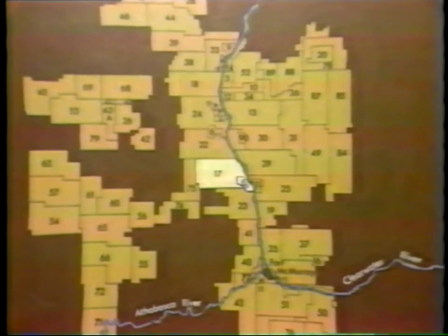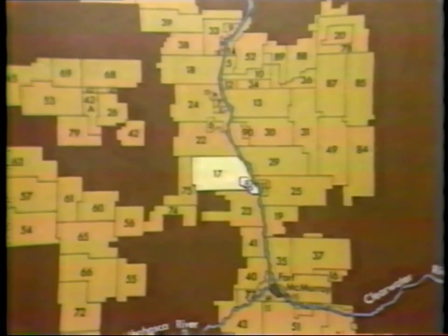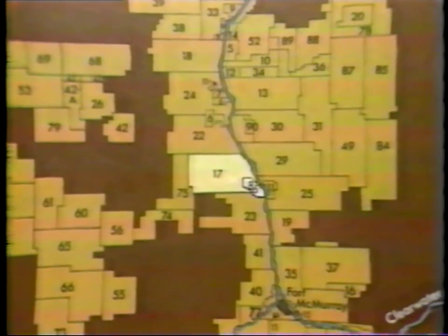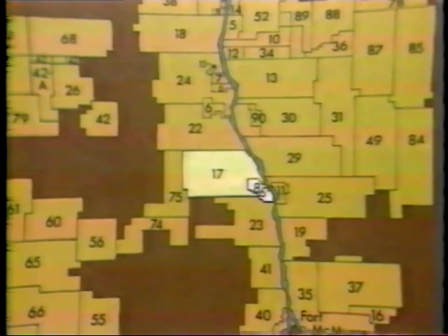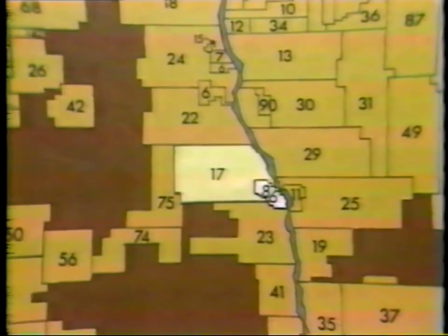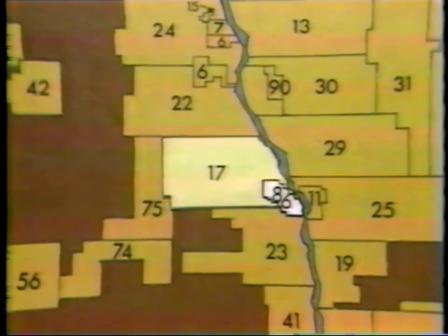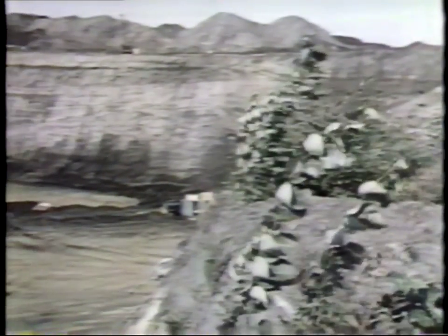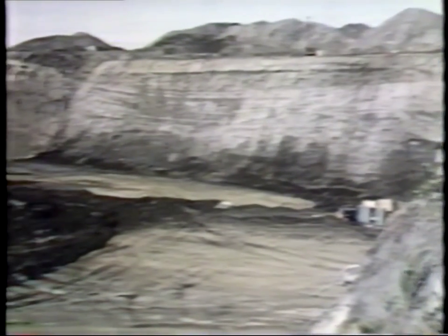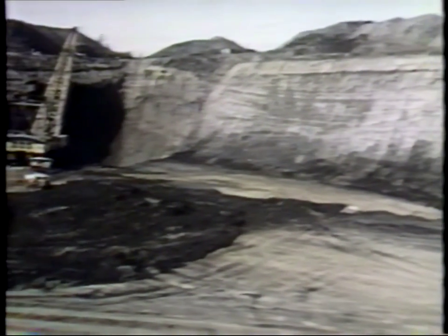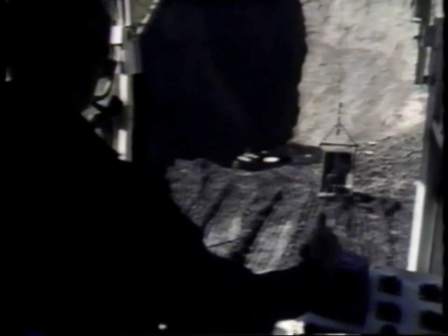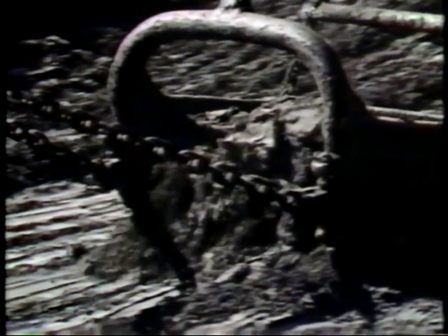The $2 billion Syncrude operation on Lease 17 will eventually extend over 12 square miles, covered on average by 5 feet of muskeg and 80 feet of barren overburden. Beneath that, the tar sand averages about 150 feet. Once again, the mining method is open pit, but instead of bucket wheels, Syncrude will use 4 80 cubic yard capacity draglines, about 5 times the capacity of this experimental dragline.